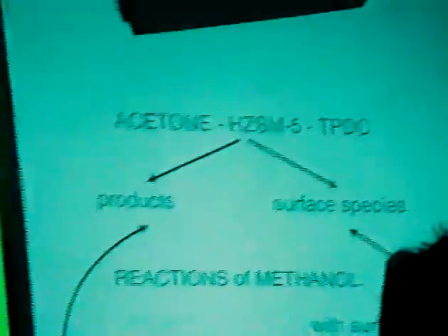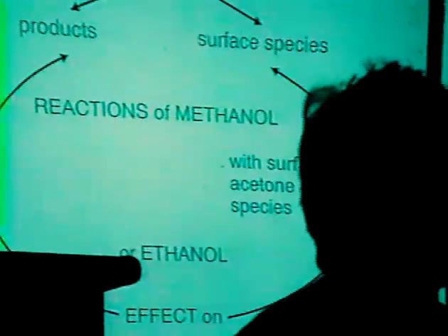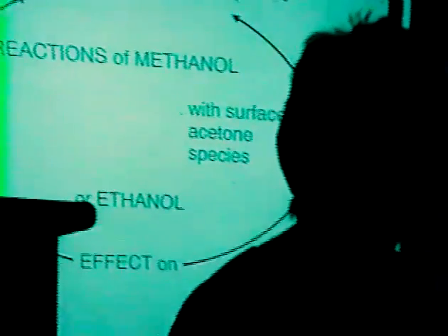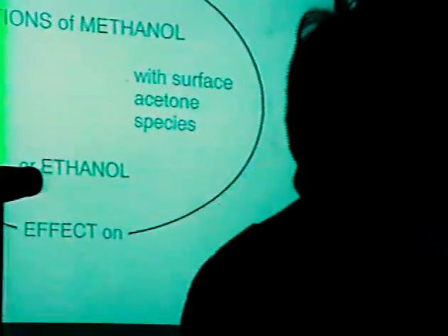temperature programmed desorption with conversion, TPDC. It means we adsorb very small amounts of reactants and then we desorb them by programmed heating. And during this programmed heating, the majority of the reactant was converted to products. We were interested in the composition of surface species and the composition of the products, at first from acetone alone, then with addition of methanol, and also naturally only of the reactions of methanol and ethanol with ZSM-5 zeolite.